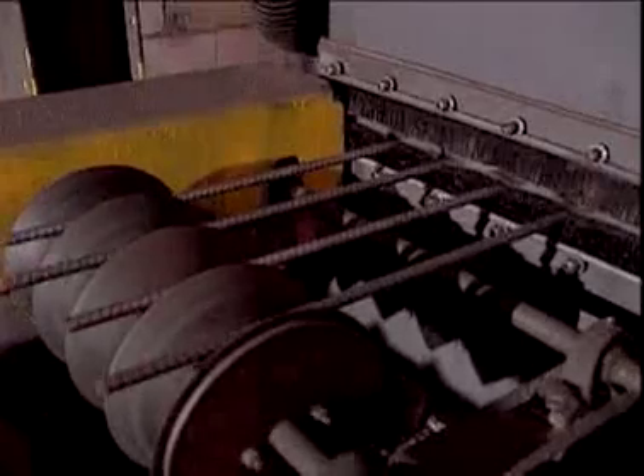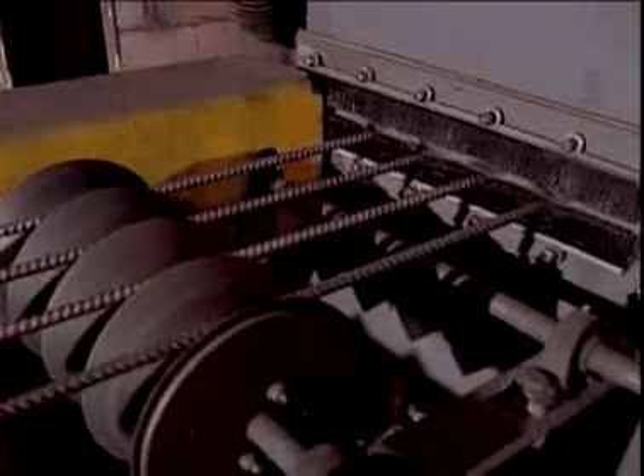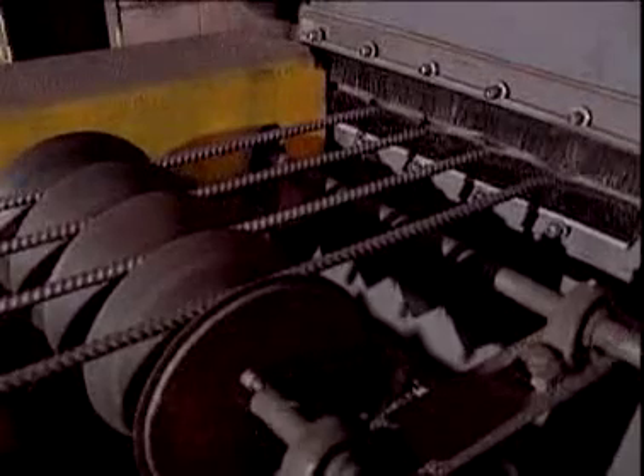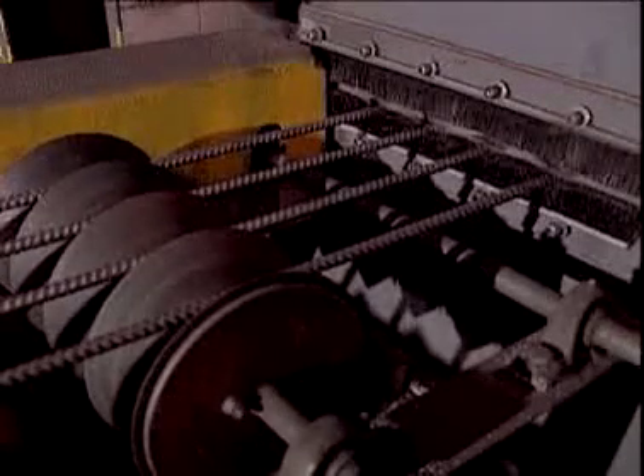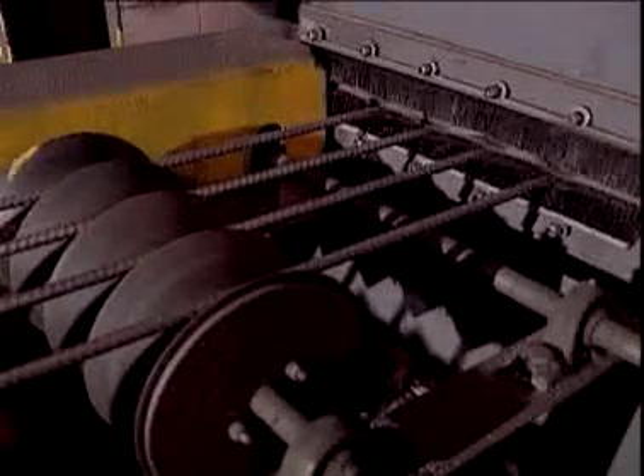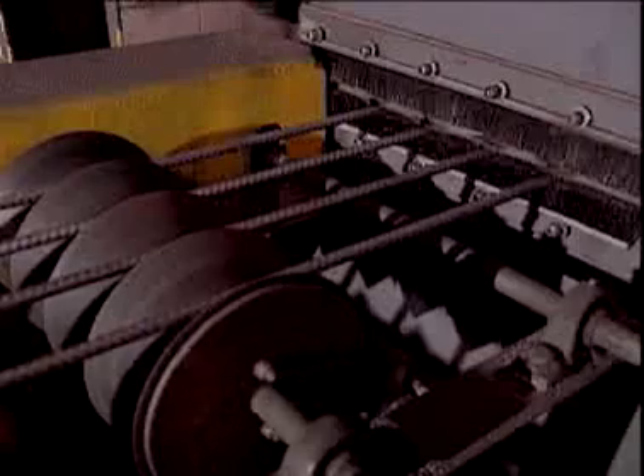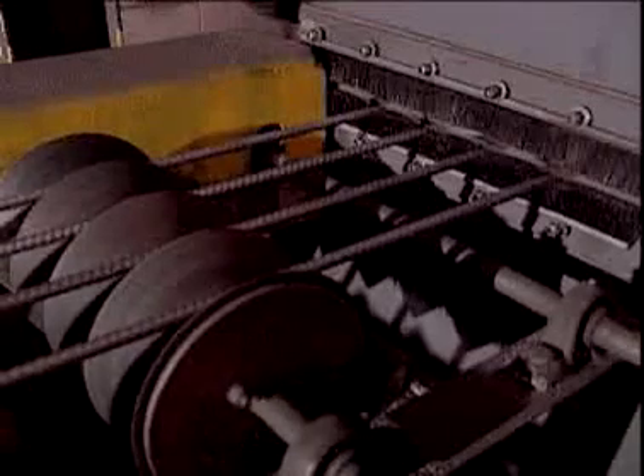A conveyor then moves the steel through a blast cleaner where abrasive steel grit strikes the rebar surface at a high velocity. Mill scale, rust, and other surface contaminants are removed. This critical step cleans as well as roughens the surface so that the coating will adhere properly to the steel and is absolutely essential to the coating quality.